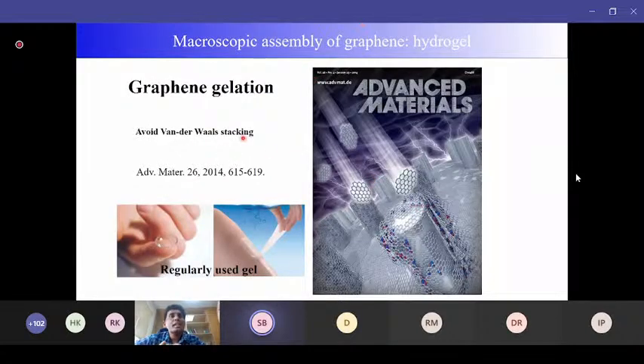In this connection, I would like to introduce one of the articles which I did with Professor Sang-woo Kim in South Korea, in KAIST. Over there, we started a technique, a macroscopic assembly of graphene. In this case, the graphene sheets are some micron size, like 10 microns or less. So the question is, can we assemble these smaller sheets into a larger macroscopic structure? And this macroscopic structure itself is freestanding, and also it retains some pore structure. In this direction, we have introduced some hydrogels of graphene.